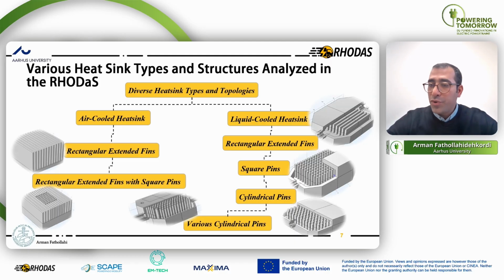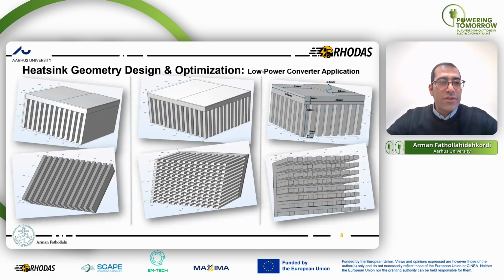The heatsink is important, but mounting pressure and thermal interface material are very important as well. Just as an example, by changing the thermal interface material and mounting pressure, you can change the heat dissipation by up to 40%. It's a lot. So let's discuss this heatsink in the low power application that was air cooled.